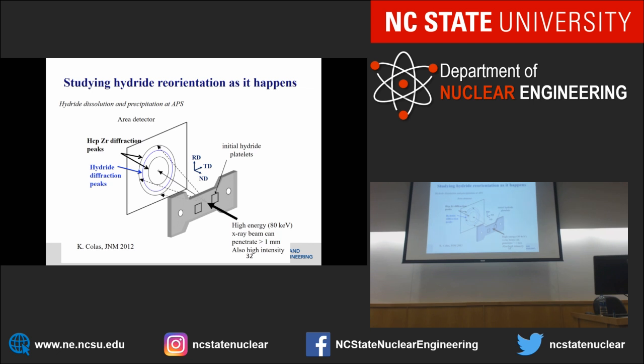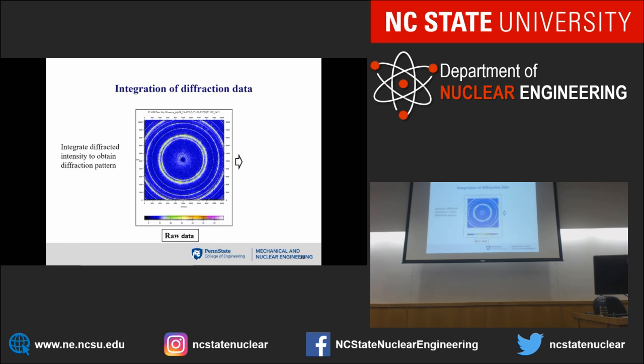And so the hydrides are traditionally platelets like this, and an area detector, and I put temperature, and as the temperature goes up, the hydrides are going to dissolve, so that blue thing is gone. When that blue thing is gone, it means that the hydrides are dissolved. And then I cool it again. Maybe I cool it under stress, and I reprecipitate it here. And I can tell when the precipitation has occurred. This is what the diffraction data is like, just rings like that, and I can index the rings to tell which phase I have. And then I integrate this, and I get a diffraction pattern like that.